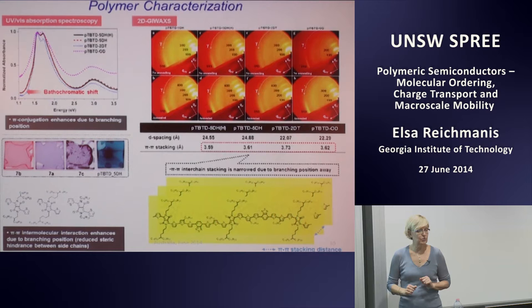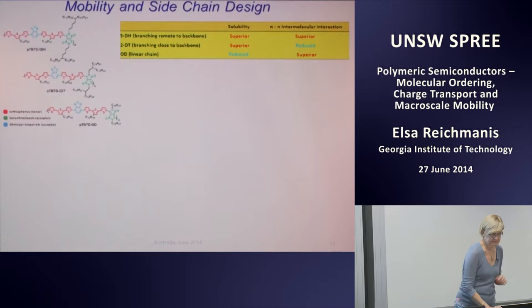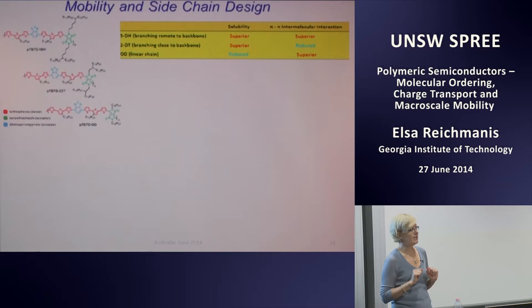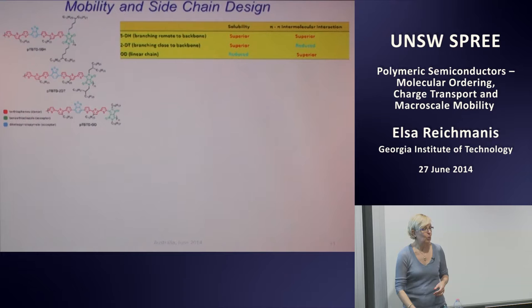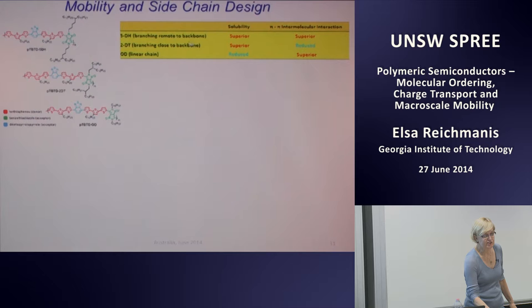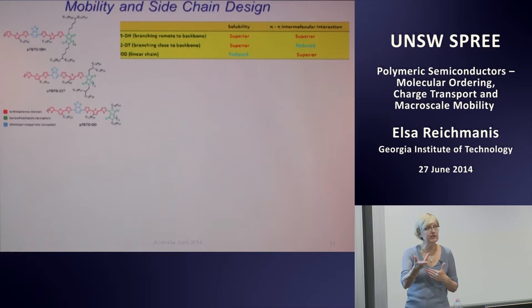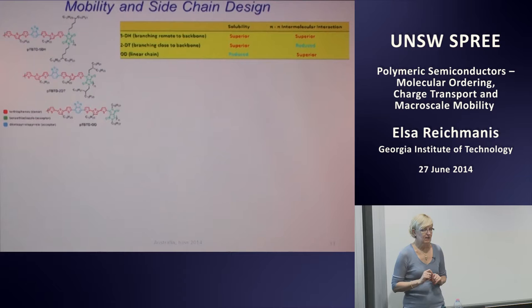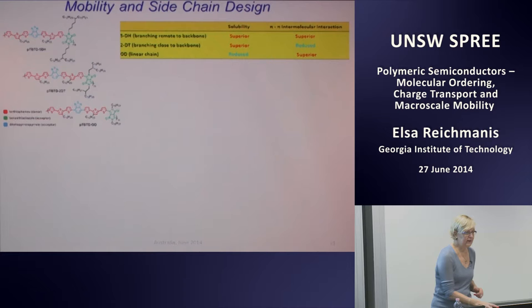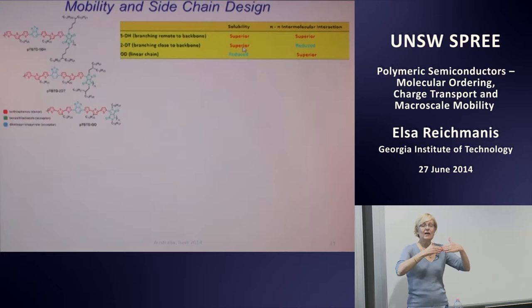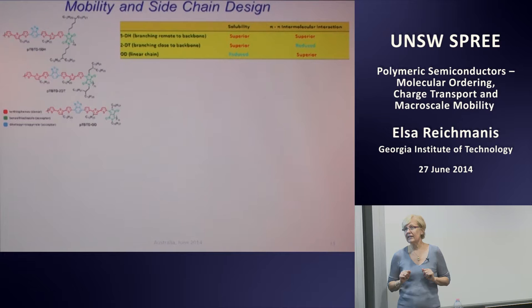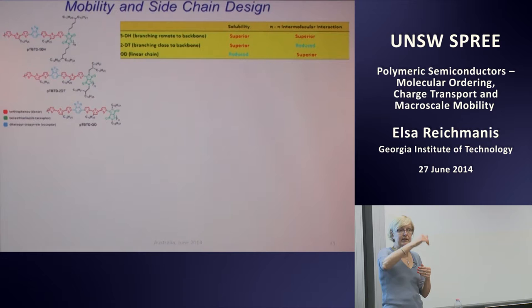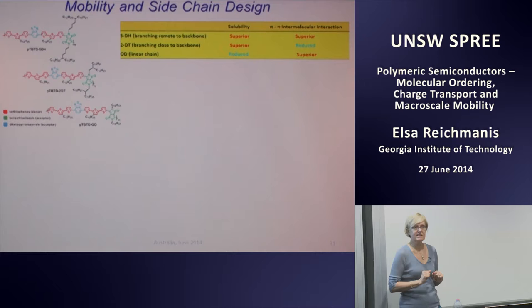Right? If we then look at the characteristics of each of these materials, largely comparing the side chain feature, what we find is that if we have a branching position that's remote to the backbone, the solubility of that material is very good in a wide range of solvents because of that branch position. Also, the pi-pi intermolecular interactions end up being very good. The chains stack relatively closely together. All right, if we have that branching point closer to the backbone, solubility is good, but the pi-pi intermolecular interactions are reduced, largely because that branching point close to the backbone leads to some twisting in that backbone, which means that when they're stacked, they have to be a little bit more separated, so the stacking distance is a little bit wider.